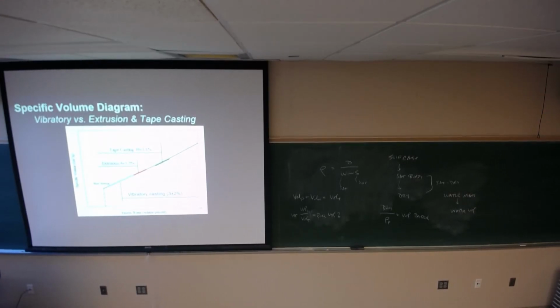In clay bodies, when you go to filter press, right, what you do is you automatically go to that saturation point for randomly oriented particles. So the system automatically goes to the right water content for extrusion. Then when you put it in extrusion, shearing lines up the particles and provides the plastic behavior for flow. So for us in traditional ceramic forming, that filter pressing step is critical. Okay? Because the filter pressing process gives me a plastic body automatically.